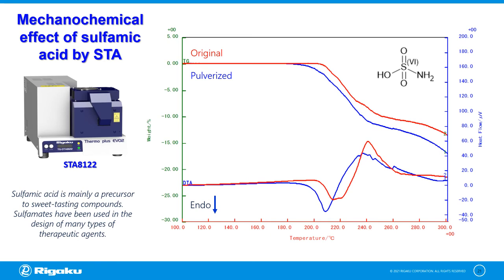The mechanochemical effect in pharmaceuticals does not only affect reactions such as phase transitions or melting behavior, but also shows a difference in thermal decomposition behavior of a material. In this case, STA is the most suitable method. Here is a multiplot of STA showing pulverized and non-pulverized sulfamic acid. The thermal decomposition of pulverized sulfamic acid starts at a lower temperature compared to the non-pulverized sample. Also, both samples show a difference in exothermic peak height near 230°C. These results show the difference in thermal behavior due to mechanochemical effect when mechanical energy is applied by pulverization.